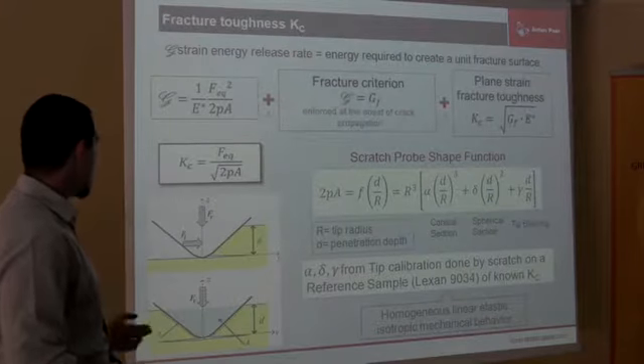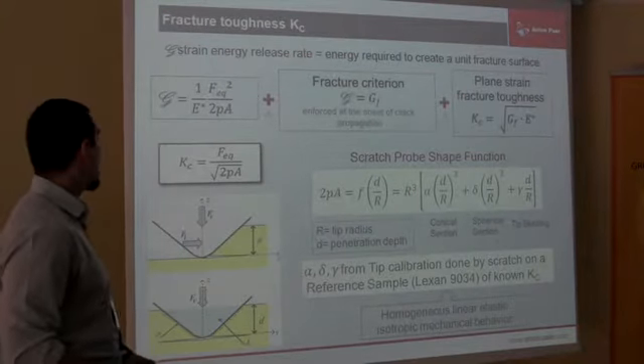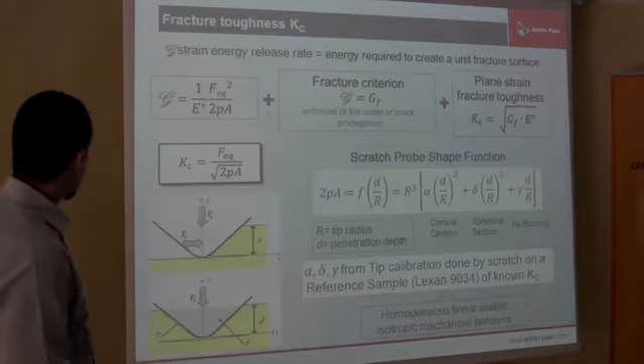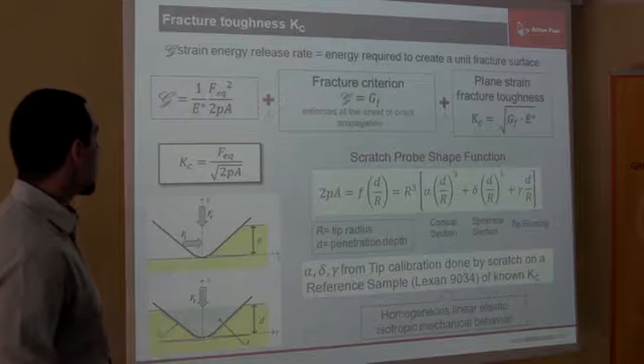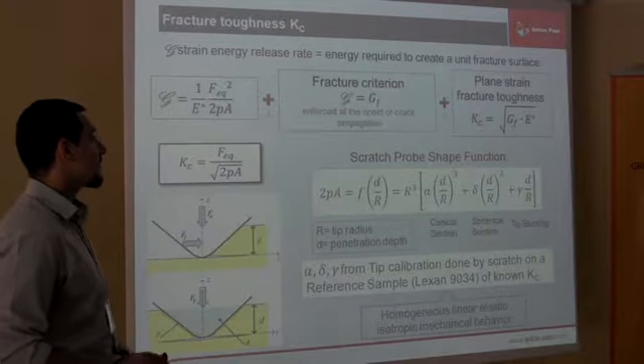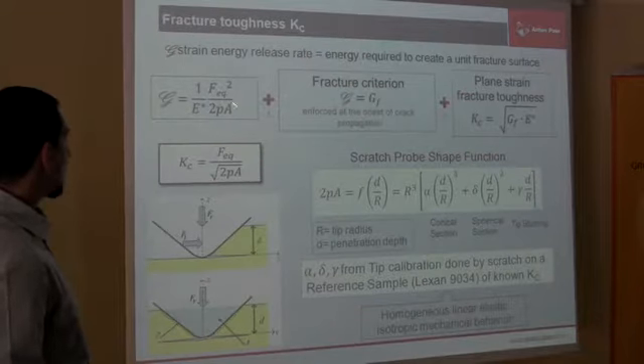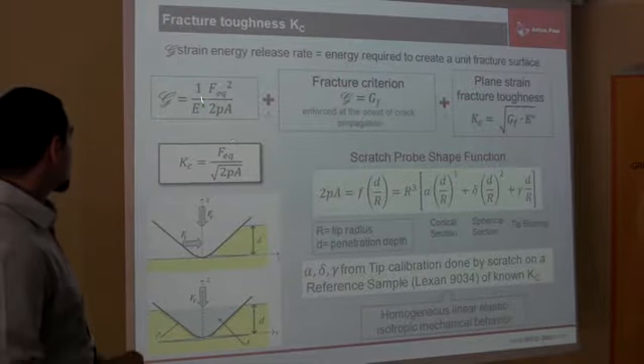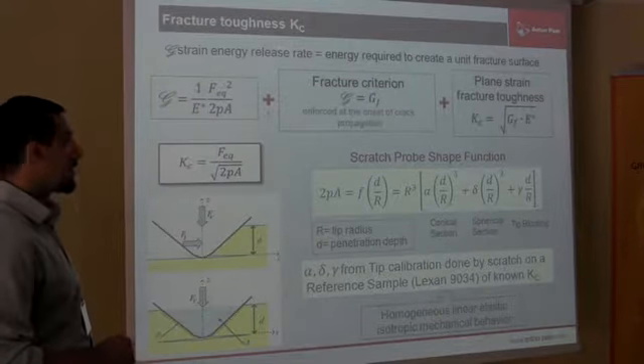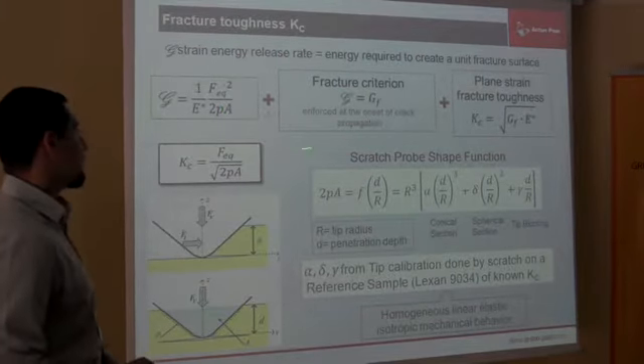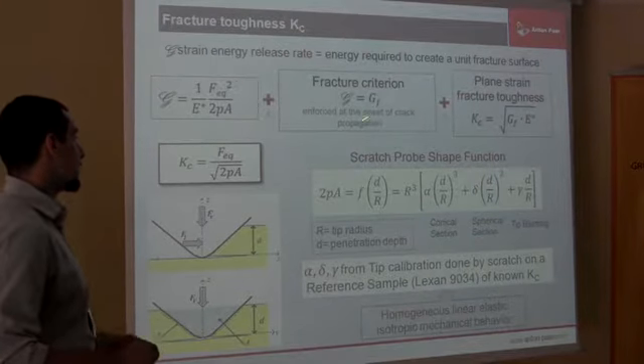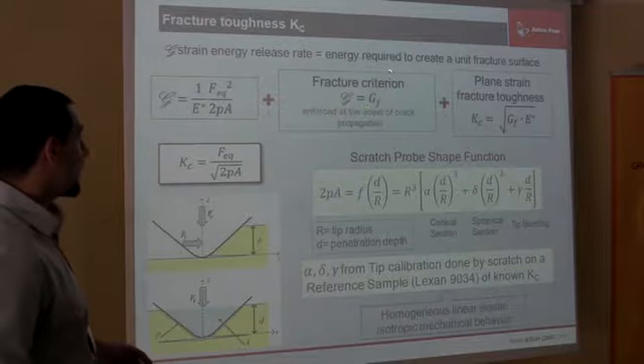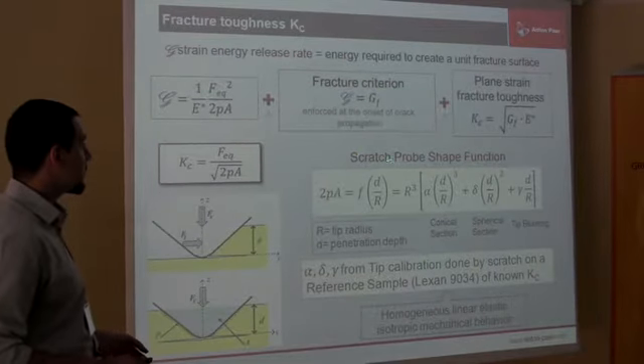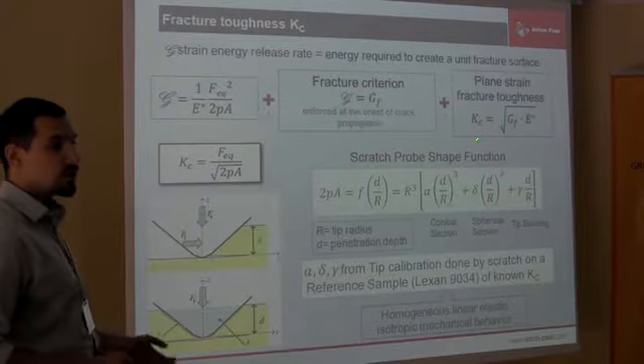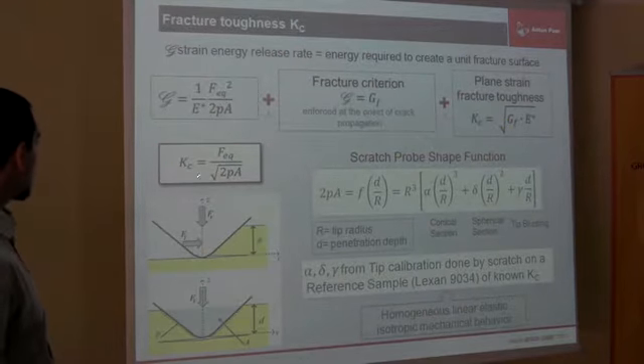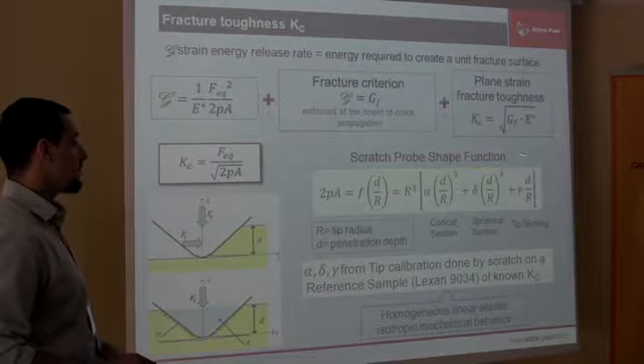So to link this property to the probe shape, we use the strain energy release, that is the energy required to create a unit fracture surface. This is linked to the scratch probe shape function, to the force applied, and to the characteristics of the material. We use that at the onset of crack propagation, in which we have a fracture criterion with G fracture, connected with the plane strain fracture toughness. In this way we can link the fracture toughness to the scratch probe shape function.